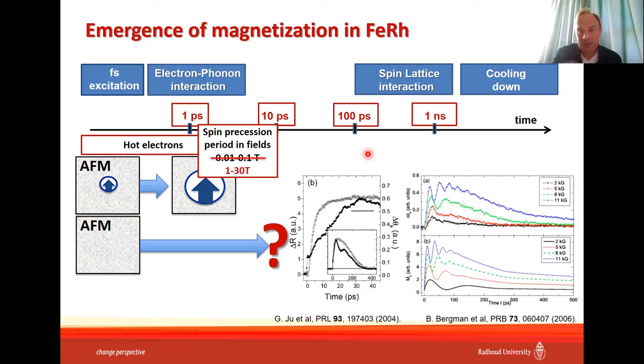So if you have a low field applied, you see the dynamics on a timescale of 30 picoseconds, and if you have a high field applied, then this increase you may even not see properly on this timescale. It's faster, but it's not strikingly fast. So all the changes are happening here on a scale of 100 picoseconds.